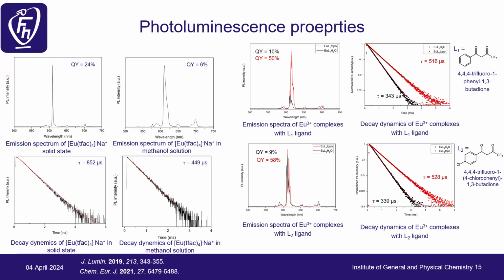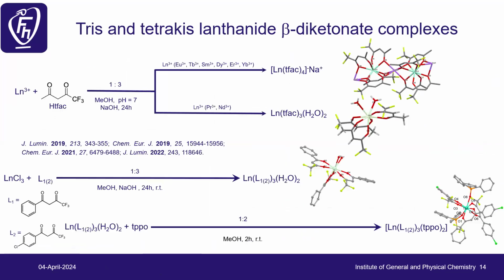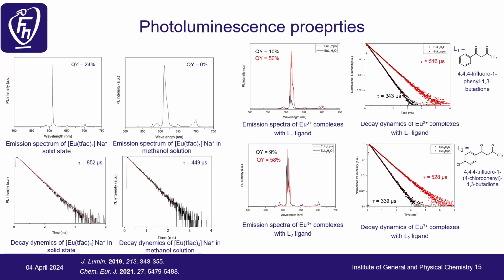And the second one is what I was talking about on the last slide. So we have a phenyl ring and a chlorine phenyl ring. We can see the increase in quantum yields by 5 times or even 6 times, and also an increase in lifetime when we add also the triphenylphosphine oxide compound, which was here. You can see it's a phenyl neutral ligand. And we see an increase in lifetime, but also an increase in quantum yields, which is quite interesting. And this was interesting for me because this gave me the opportunity to play with it for sensors later on.